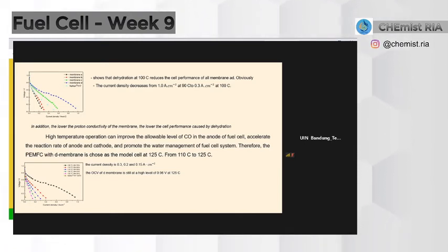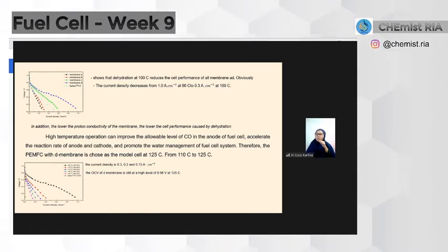Okay, next. In this figure, we can see the current density is 0.3, 0.2, and 0.15 respectively. The cell with Nafion 117 membrane can hardly output any power at 120 degrees Celsius due to its loss of conductivity. In addition, the OCV of the membrane is still at a high level of 0.98 volt at 125 degrees Celsius, while that of Nafion 117 is only